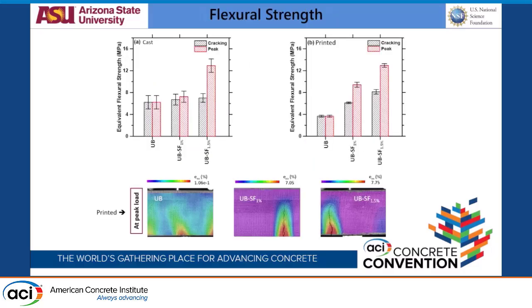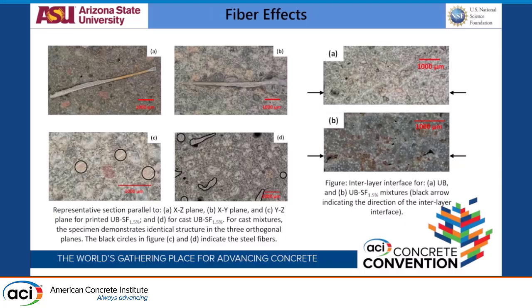Now, why does that happen? Again, these are the flexural strengths of the samples. From DIC we see high strain concentration during the peak load, and we have more ductility. But why does the strength differ like that between the cast and the printed? We cut cross sections out of our print sample versus a cast sample, and took another microscopic image to see how the fibers are oriented along the print direction. The top two are a transverse section cut along the print direction, or length direction, of the beam. You see that in these sections the fibers are mostly directed along the length of the beam. If you cut a cross section perpendicular to the length direction, you'll see circular kind of fibers in the cross section, which shows that the fibers are more oriented towards the length direction.